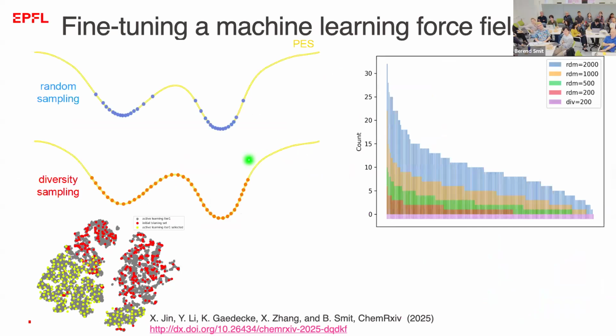If you don't do that, and that is what most previous studies do, for example, you sample your configurations at random for which you do a DFT labeling. What you then typically see is you sample the most common very frequently, but that contains very little information because they're all the same. What is really important is that you also sample the barriers. And for that, you really need to do some affirmative action.